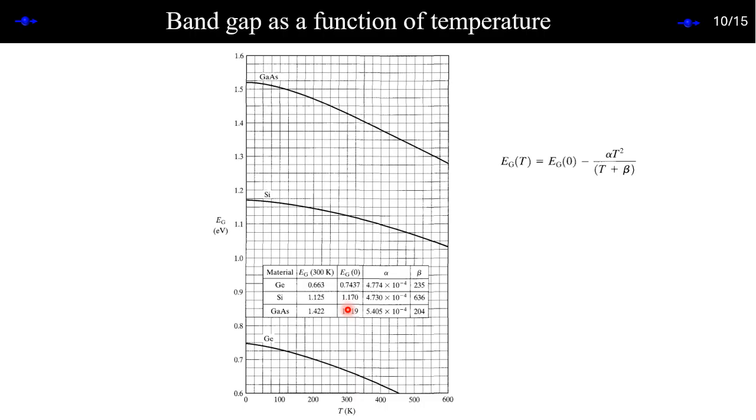And if it gets broader, suppose we have 2 bands here, right? Okay, we have 2 bands. If it is broadened, then they will be closer. If they are closer, then band gap automatically decreases. There is no mathematical analytical form of it. So people have done experiments and they came up with this kind of expression, okay, by fitting.